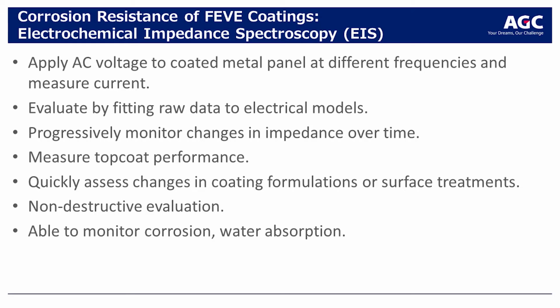In the first 2 test types, you're scribing that coating, so what you're really testing is the efficiency of the primer at preventing corrosion. What we're interested in is what the top coat contributes to corrosion protection, not the primer. That's a lot harder to figure out. So there's a test called electrochemical impedance spectroscopy, or EIS. It's being used more widely now for corrosion testing.